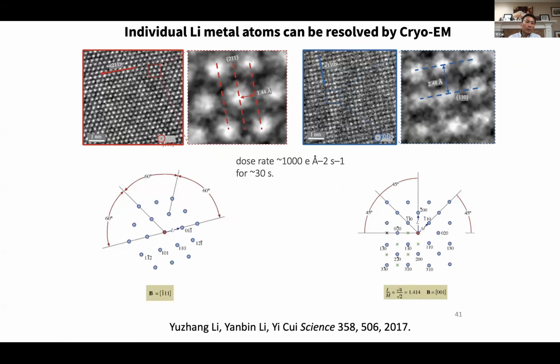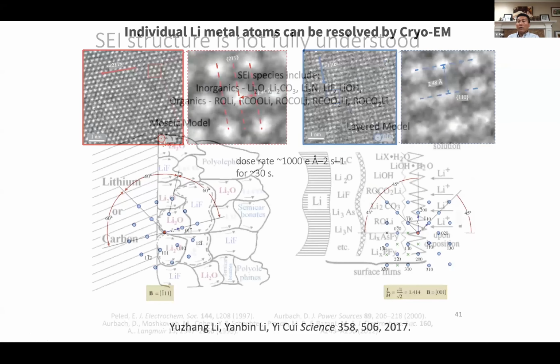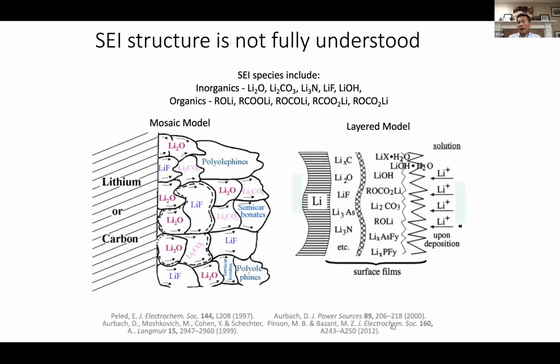Lithium metal has a melting point of about 180 degrees Celsius, right? As soon as you focus your beam under the normal TEM, you're going to damage that. But in the cryo condition, we were able to obtain atomic scale resolution. And this also allows us to look at the SEI, solid electrolyte interphase, stabilize the interface, and study that. There are 2 models of what the SEI structure is right there. And this certainly is a debate.